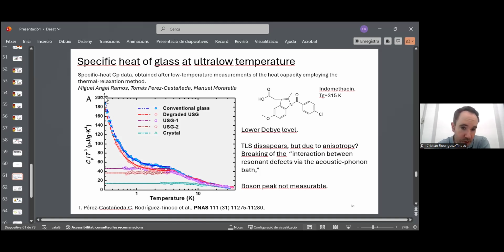This is a conventional glass. The blue points are conventional glasses, so the typical behavior of a system with TLS, the typical behavior of an amorphous system. But these purple points and also these ones are two ultrastable glasses. Here we observe that we don't have any signature of TLS. It was a striking observation. In the case of the ultrastable glass, we observe an absence of two-level systems. So this anomaly, which is universal in glasses, is not observed in the ultrastable glass.